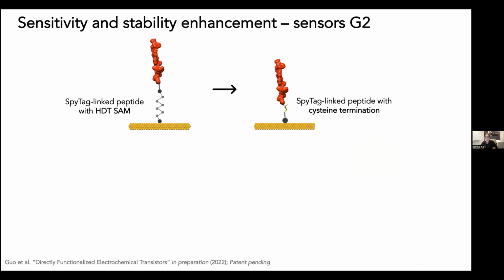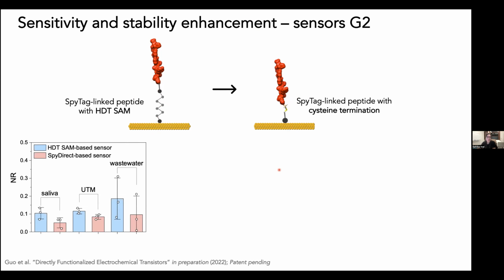For example, by changing the way we immobilize the biorecognition unit on the sensor surface, we managed to bring some extra features to the sensors. For instance, if we don't use this HDT, this carbon chemical layer to anchor the protein, but instead use a peptide, sorry, that has a cysteine termination, we can anchor the nanobody construct directly on top of the gold surface. We saw that this is very useful to lower the background noise which uncovered HDT gives, especially in very complex samples such as wastewater. So for these cases, we see the advantage of using a direct coupling of the peptide unit to the gold electrode surface.